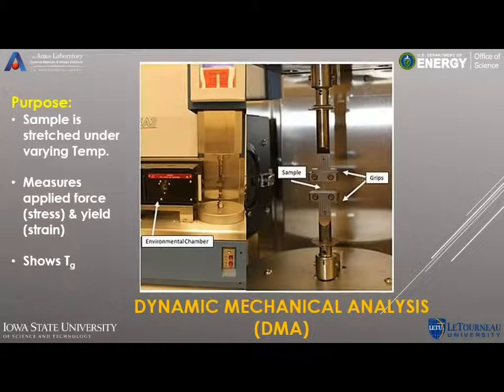Now another test we did was dynamic mechanical analysis, abbreviated DMA, and that stretches the sample over a range of temperature to see how much force it can withstand before yielding. This is done to measure the glass transition temperature, or the point at which the sample changes from a stiff state to a more rubbery state.